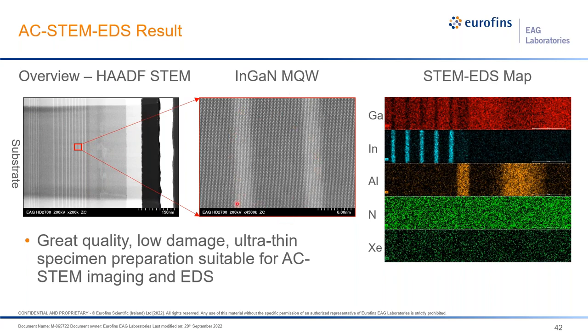And so really the result here is that you can create great quality, low damage, ultra-thin samples that are suitable for aberration-corrected STEM imaging and EDS, EELS. Here on the right, seeing the STEM EDS map as well. It's still not completely understood, at least for specific samples, the improvement in the analytical ability from not having gallium.